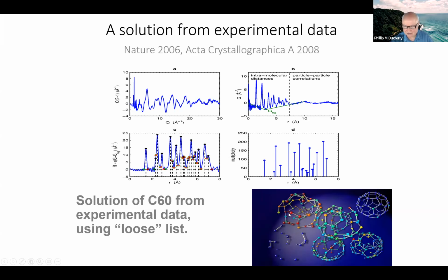And so the result of our algorithm at intermediate stages is shown in the figures at the bottom right. And this is from just this data. There's no other information input here. And even the number of atoms is allowed to be flexible. What we do is watch the error in the reconstruction, and the lowest error is the final structure at the top right of that figure. So that was very encouraging.